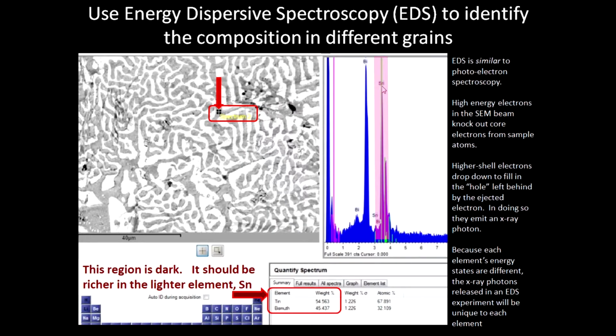So here's another one that is labeled as tin. These green lines, you can just ignore them. Those are just to help me identify what the elements were at those different peaks. But you can see that I've only shown part of the spectrum down here. There's a couple different peaks for bismuth over here, and there's a couple peaks for tin. And those are characteristic of those particular elements. So only bismuth gives a peak at that particular X-ray frequency or X-ray energy. And so once that has been programmed into the computer, it's really easy for it to give an identification of what elements are present that might be giving off those X-rays. It's really pretty cool.